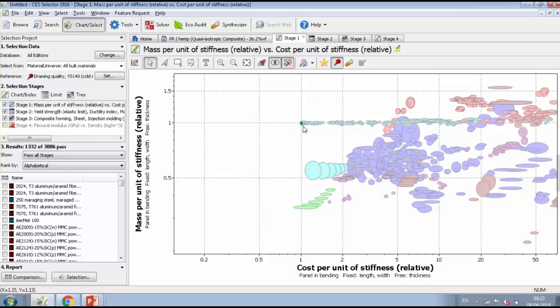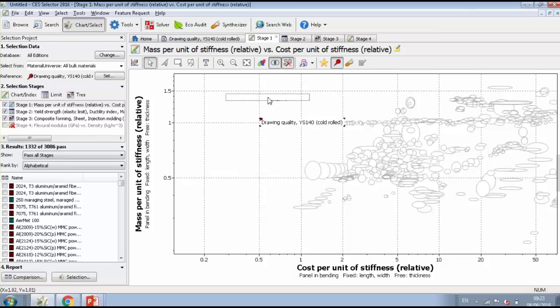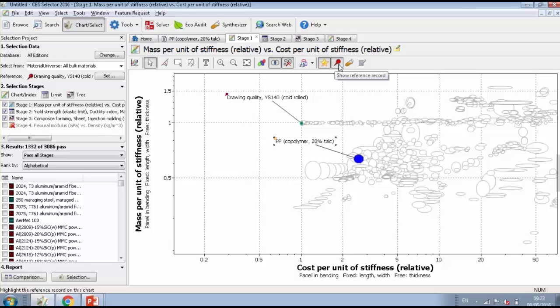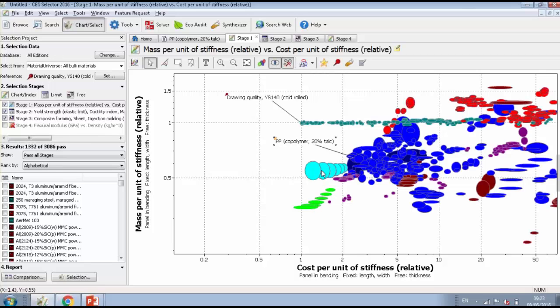So our initial material, this is the steel. I can highlight the copolymer, the talc-filled polyprop, which Smart's been using. But very quickly, I can start to see, this was the sisal. This is showing not much benefit from increasing the fibre content. It doesn't really reduce the mass of the component. But I can see that this hemp-filled one is much better, and also it's much better than the aluminium alloys. This is a significant weight saving, and it also outperforms the magnesium alloys. So this has given me a good amount of confidence that this material is worthy of further investigation.